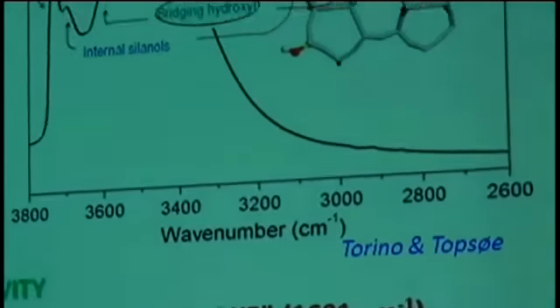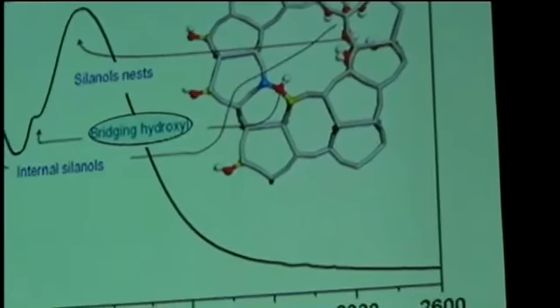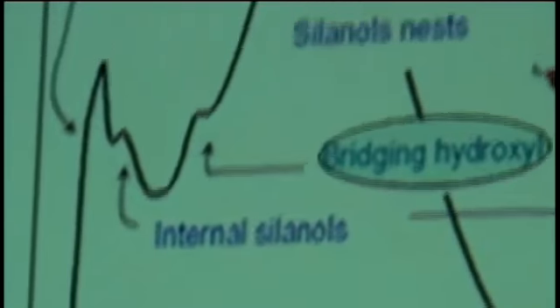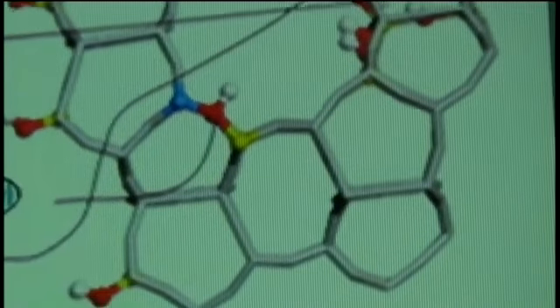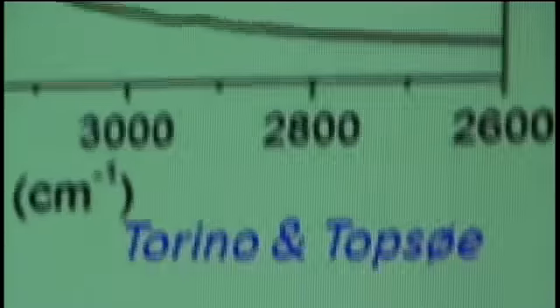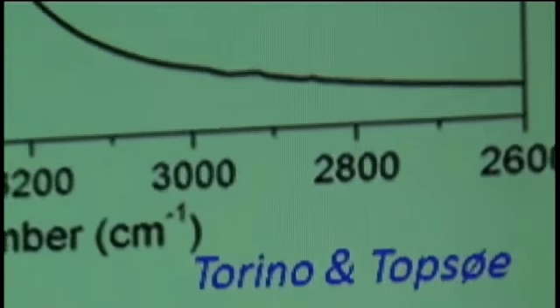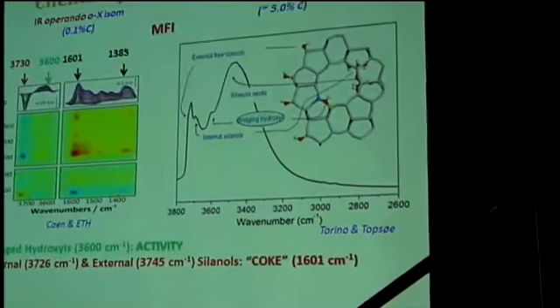And I spent a few hours one day with Pablo Beato in Lyngby, and I showed him these results. At that time he was working with in situ infrared with the people in Torino, with Silvia Bordiga, on MTO, and he jumped and said, okay, I understand my results, you have exactly the same thing as I have. Your coke is also going on the external free silanols and also on the internal free silanols. So if you want to prevent coking, decreasing the number of defects, decreasing the number of silanols, whether external or internal, is a good thing to do.